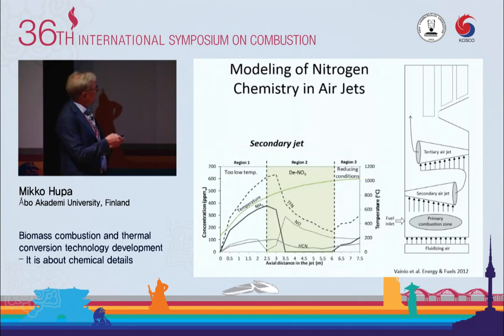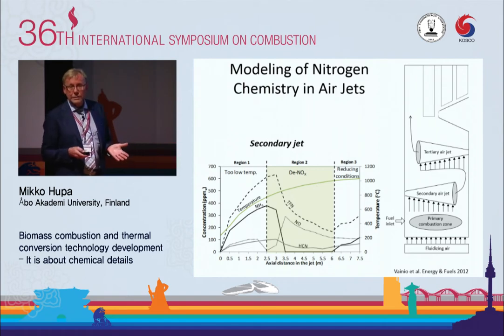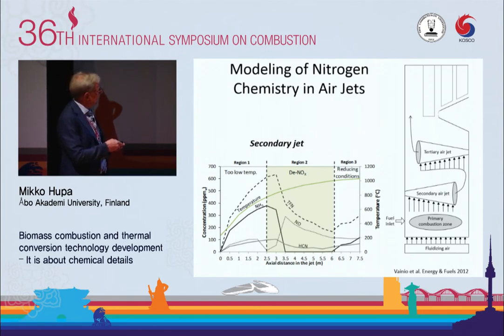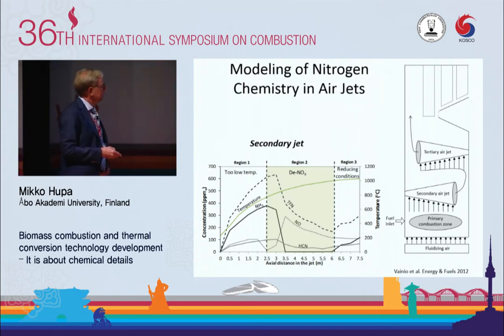So we wanted to see what happens to that gas when it's going into the jet. And here, the temperature increases until we come to somewhere around 800. And in this period, 2.5 meters, chemistry doesn't play a role yet. It's frozen, it's too cold. But then at somewhere here, the chemistry starts playing a role, and we see that the entrained ammonia suddenly disappears. Some NO is formed, and then they both disappear. So there is a steep decrease in the total fixed nitrogen until we have used all oxygen in that jet, and the final part, no chemistry anymore, only entrainment of new flue gas.